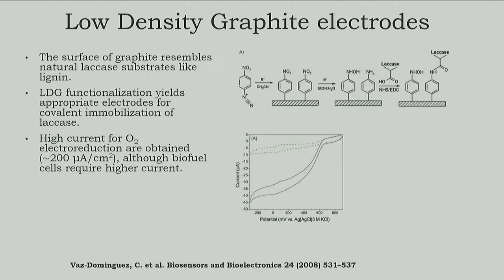Okay, so when we do this, this is the reaction we get. We are not feeding this with lignin or any kind of phenols, but when the enzyme is immobilized on the surface, what we get is a potential of 600 millivolts plus 200 from the reference electrode, like 800 millivolts. We're going to get a cathode that reduces oxygen at such a high potential. This is very unusual, and normally in fuel cells with different kinds of catalysis, this process starts at a lower potential. So those batteries are going to have a more difficult, lower applied potential. In this system, by making this easy reaction, we achieve like 200 microamperes per square centimeter.